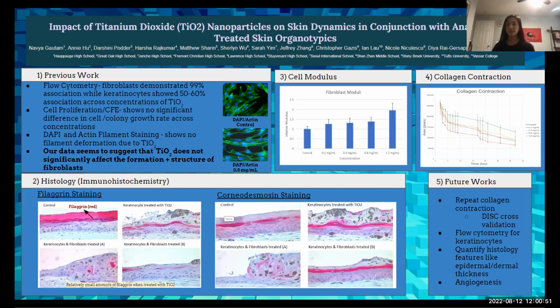Corneodesmosin is a protein integral to localizing the stratum corneum at the top of the epidermis. The protein is found in the stratum granulosum, which we can see demarcated in red after staining for corneodesmosin. In both the control and TiO2 treated keratinocytes, this layer appears maintained, although the stratum corneum may form aberrant structures above it. With both keratinocytes and fibroblasts treated, we still see a distinct layer except for in image A. So we can conclude that TiO2 treatment doesn't have too much of an impact on corneodesmosin expression, and thus some regular cell dynamics may be preserved.